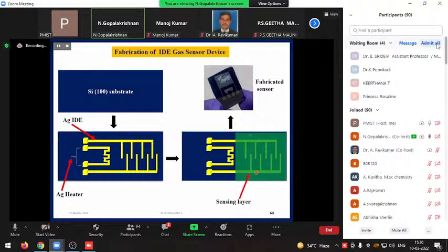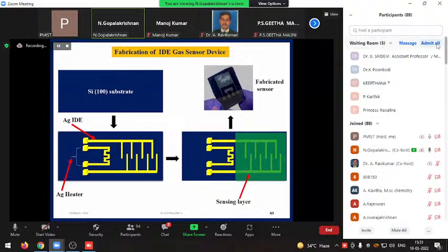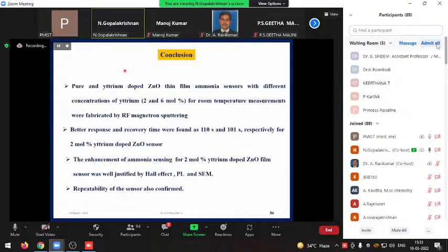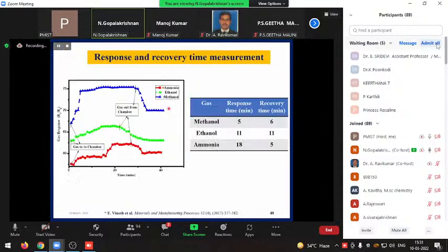Then we made the film on the IDE substrate, because there is a large electrode surface area, whereas in the previous case we simply dropped the film on the substrate. Since the electrode surface area is very high, when we expose the gas the efficiency is higher. That means we prefer the interdigital electrode sensor device over the previous thin film sensors. We exposed different gases as in the previous cases and measured the sensor response, and we found higher efficiency and more response than in the previous case.